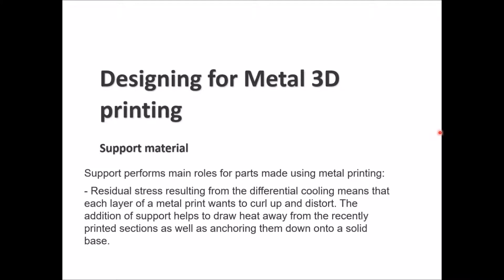The residual stress is a concern as well for this kind of technology, because residual stress results from the differential cooling, which will make each layer of a metal print curl up or distort. And you need in this case to add support so that you will help draw the heat out of that layer, so that it will be sealed down in place and will not do any kind of curving or curling or distortion during printing.